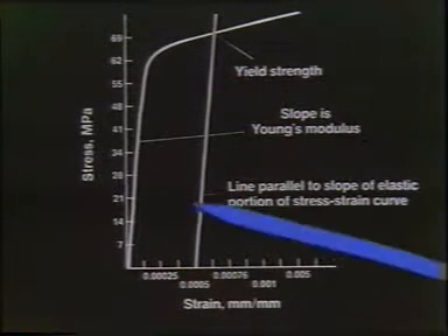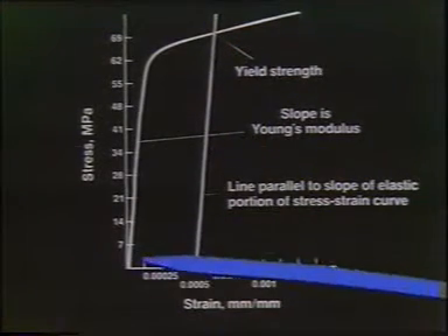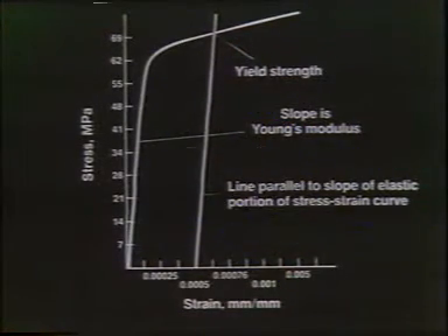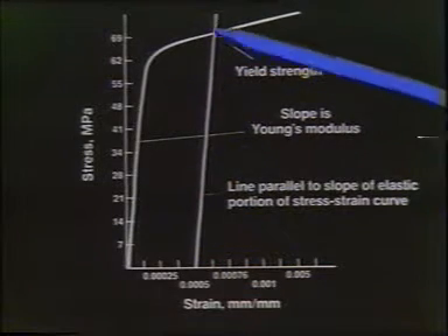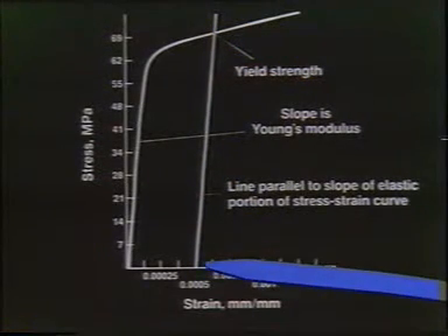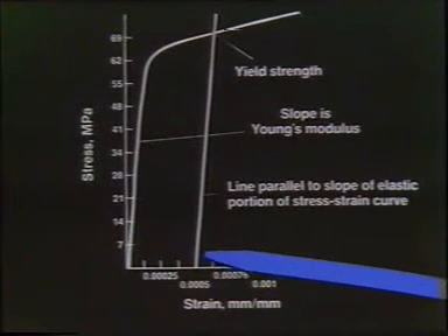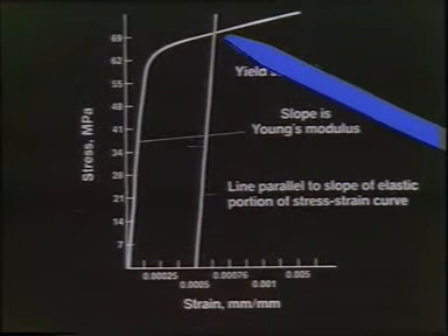And so now, if we take the curve, draw the elastic modulus parallel to the loading modulus, we haven't unloaded this, we're just interested in that intersection point. If we took this value, let's say at 0.2% offset, 0.2% strain offset, we could specify a yield strength at 0.1% offset. That would be up to whoever wants to do the designing. But that particular value where it intersects is called the yield strength.